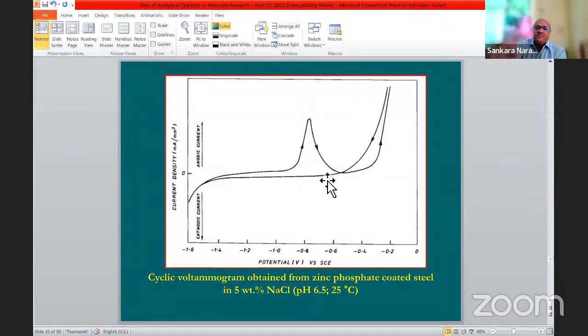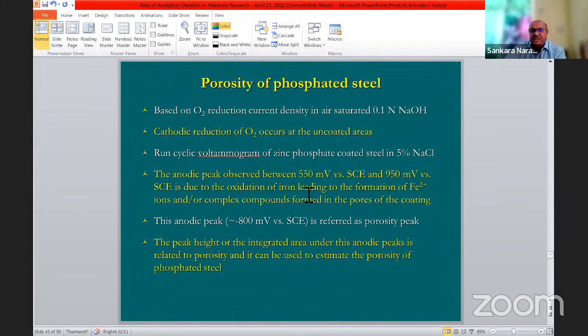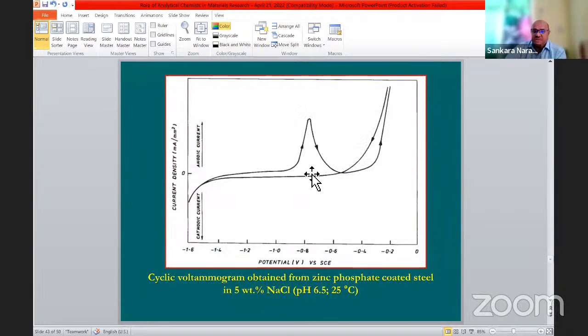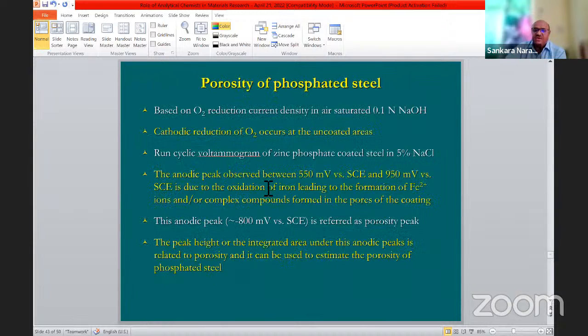That can be referred to as the porosity peak. So this is the peak. You can see it around 800 millivolts. You can see a peak, an anodic peak, and that is mainly due to the dissolution, the oxidation of iron, leading to the formation of ferrous ion, or it might form some complex compound in the pore itself. So we can use the peak height or the area under the peak, and that can give you a measure of the porosity of the phosphate coating.